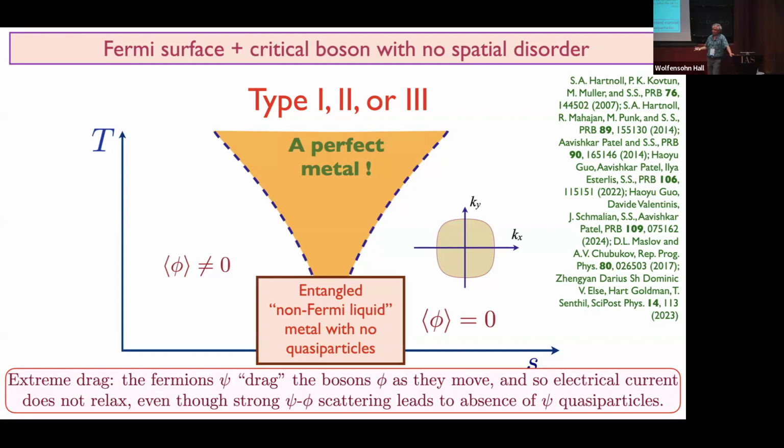Now, why was Bloch right experimentally, even though his theory was wrong? Well, for two reasons. One, the electron-phonon coupling is weak, and two, there are always impurities. The impurities will relax the momentum, and since an electron scatters off a phonon only rarely, in between two scattering events the phonon has plenty of time to find an impurity and dump its momentum there.